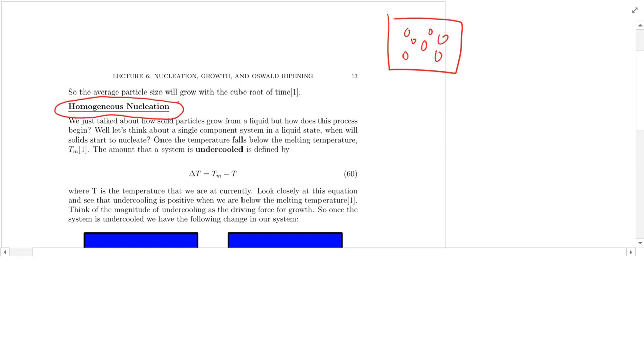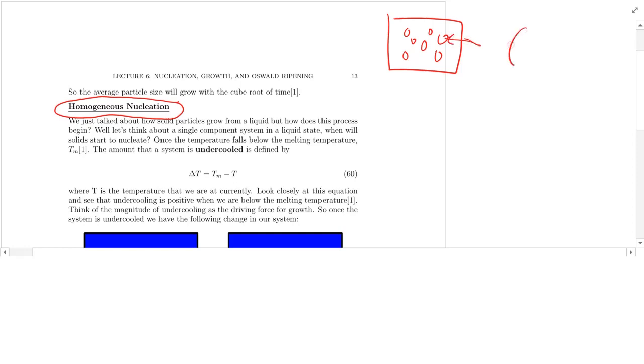We know from thermodynamics, from lecture five, from phase diagrams, that depending on the temperature and composition, what fraction of which phase will appear. But fundamentally, thermodynamically, why do they occur? Why do we want to form this solid? Because when we form these solid precipitates, there's going to be some area that separates your liquid and solid — that creates an interface. Creating area is bad because we have to pay the energy penalty, so your delta G is going to increase. So why do we form a solid to begin with? What's the driving force?